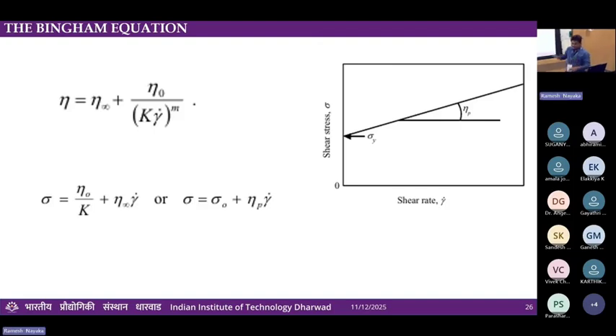Again, if you want to measure that in rheology, then you have creep. Over the rate of setting, there is creep, which is how much it will deform. Deformation is also allowed at a certain level. But when the load is applied and it is completely compressed or shrunken, in such a case it is definitely not taking the load. You prepare your mix design in order to take those loads in the fresh state as well as the hardened state. While printing, it is in a fresh state and that should resist.